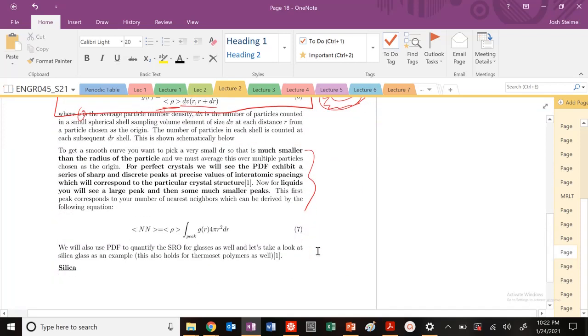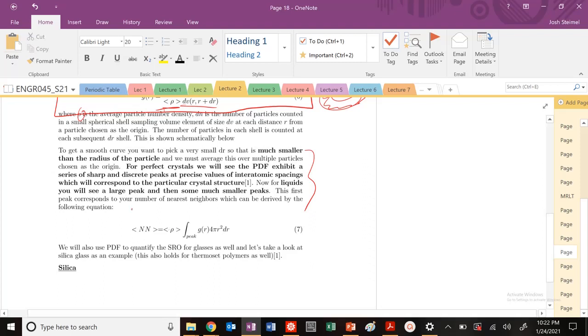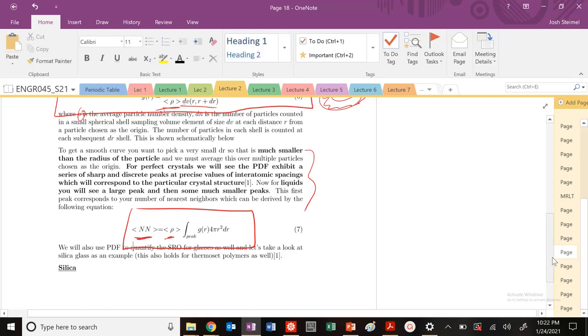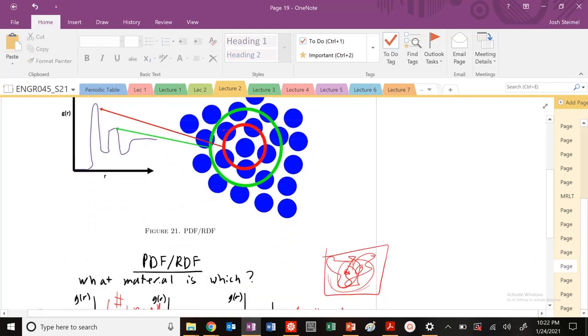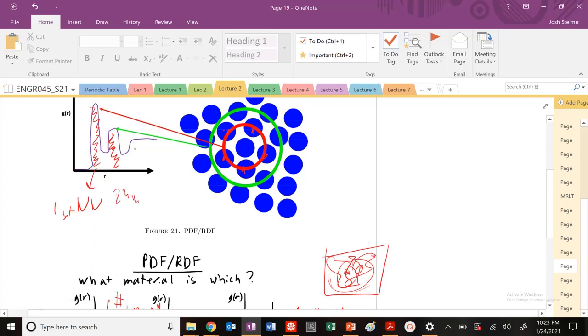And you could even get further information into these peaks. So, for example, if I integrate your peak for the first peak, I can figure out the integral of the peak is going to give me the number of nearest neighbors. Because, that's what we're doing, essentially, in this PDF and RDF. We're counting the number of atoms that we're hitting in the shell. So, if I integrate this peak, that's going to give me the number of nearest neighbors, my first number of nearest neighbors. This, if I integrated this peak, it would be my second number of nearest neighbors, my second coordination shell, et cetera, et cetera, et cetera.